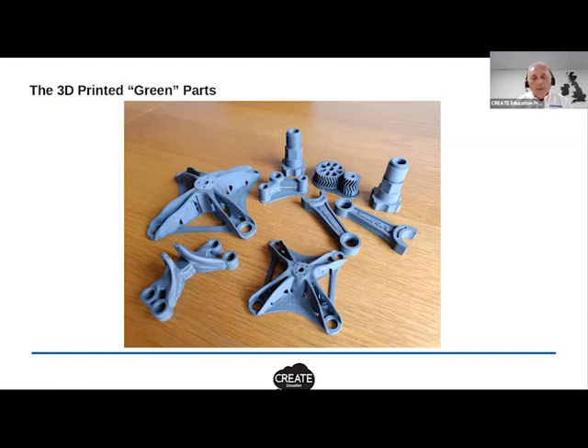So this is how they look when they're 3D printed. The key part is, how do we then extract the polymer from these finished parts and then turn them into the final metal part? That's a process called debind and sintering. In this case, debinding is a catalytic process. It uses a nitric acid environment to effectively extract the POM polymer. It changes the POM polymer into formaldehyde, and then that gets extracted out. So that's effectively taking the polymer content out of the parts during debinding.